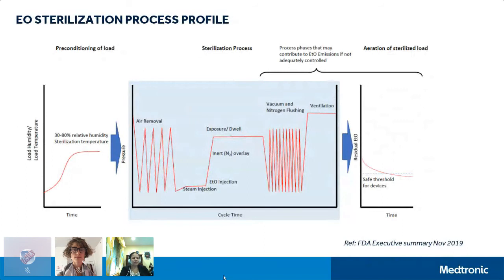And to be able to do that, there are a number of safety measures and controls, and there is continuous monitoring of parameters, temperature, pressure, gas concentration, and time, throughout the process. The third step and the most important step is the aeration phase. This is where the product has completed the EO process, but still has some absorbed residuals. During this phase, additional processing is performed to reduce the residual levels to a minimum, to the required standards. This is a highly controlled and monitored phase, because if there is any shift in the process, you might see an increase in the EO emissions.